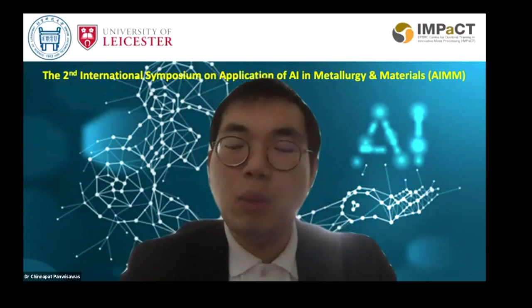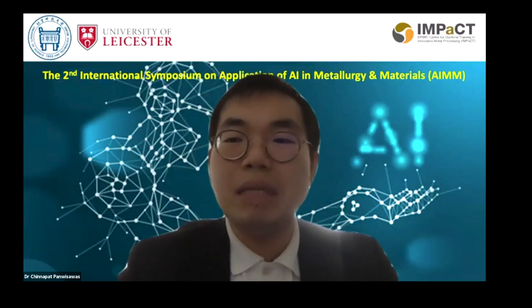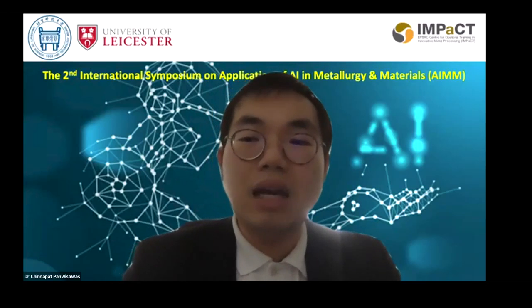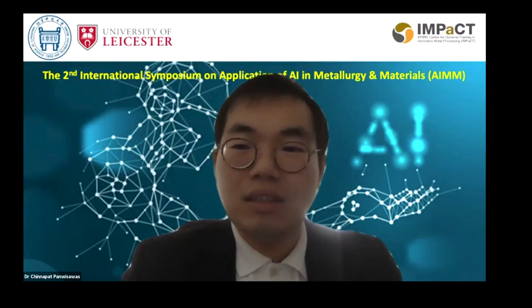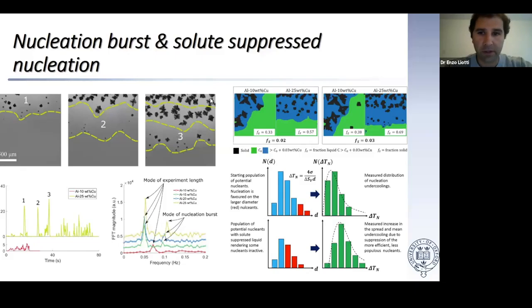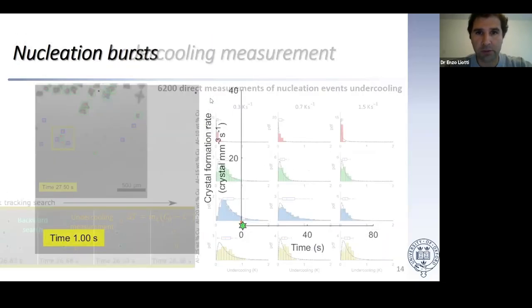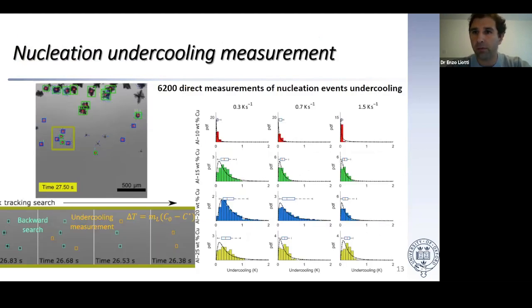Someone is asking, could you please elaborate a bit more on the combined effect of cooling rate and undercooling on nucleation? You can show your slide if you want. So I think the effect of cooling rate is interesting because what is known by theory and by experiment is that in any casting, if you increase the cooling rate, you end up with a smaller grain size. That means that you got more nucleation.